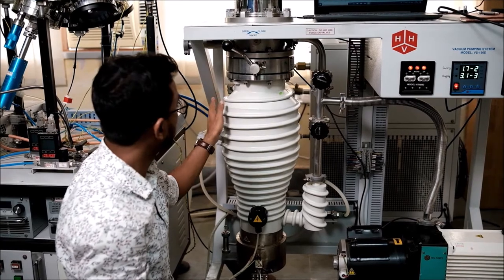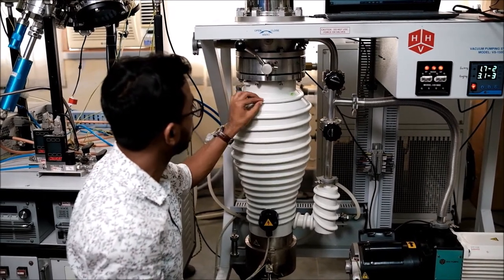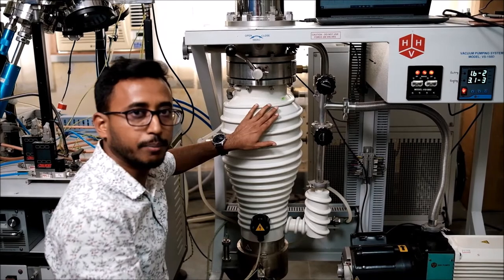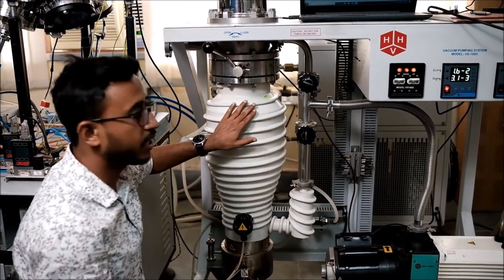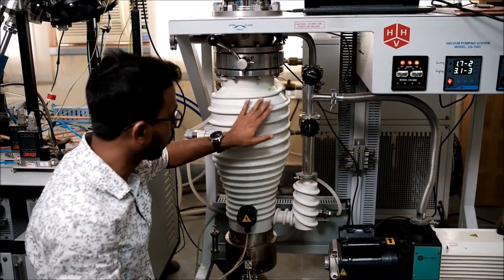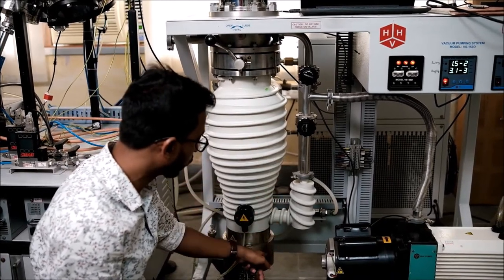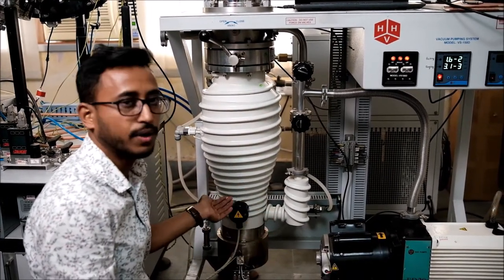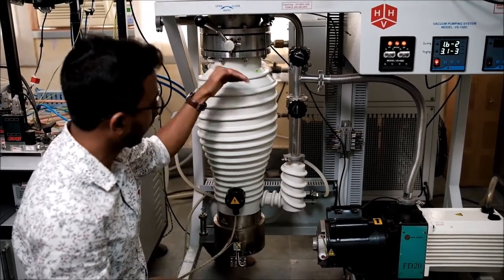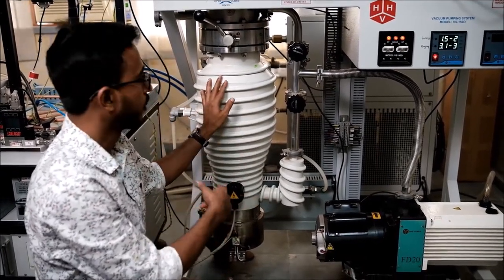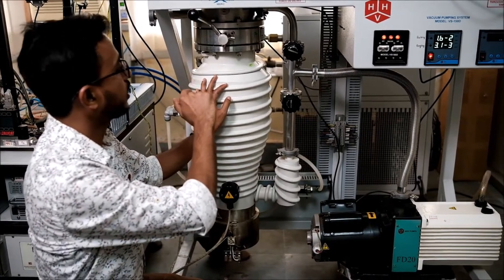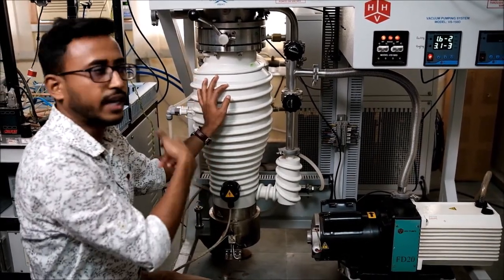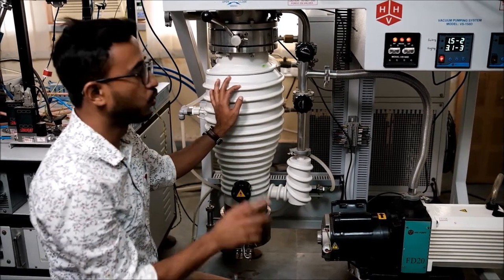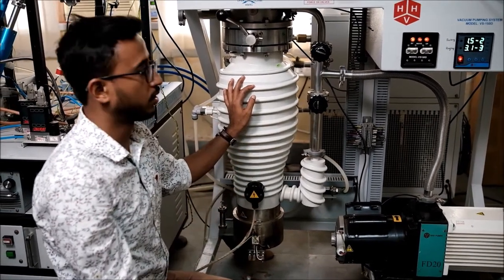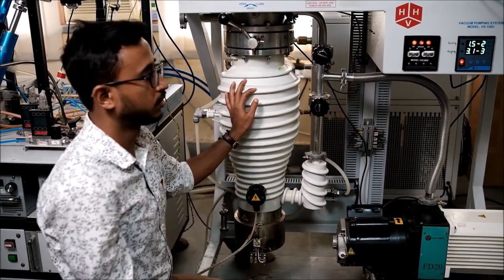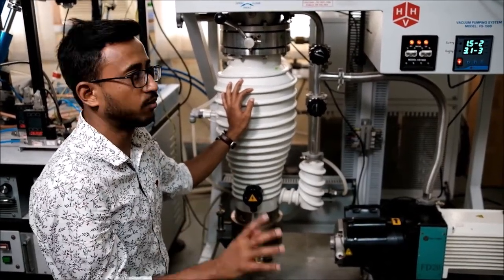And at the wall of the diffusion pump chamber, chilled water is passed through so that the wall is maintained at low temperature, so that the vaporized oil can be condensed into a liquid form and again goes back to the bottom stage. Then again it heats up and forms a vapor and then jet, then again condenses, and this cycle goes on. This way we get a very low pressure, and for this chamber it takes more than an hour to go to the 10 to the minus 6 millibar of pressure. So we will meet after some time when the pressure reaches the 10 to the minus 6 level.